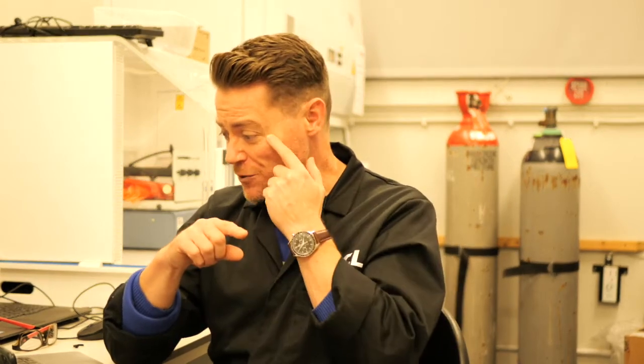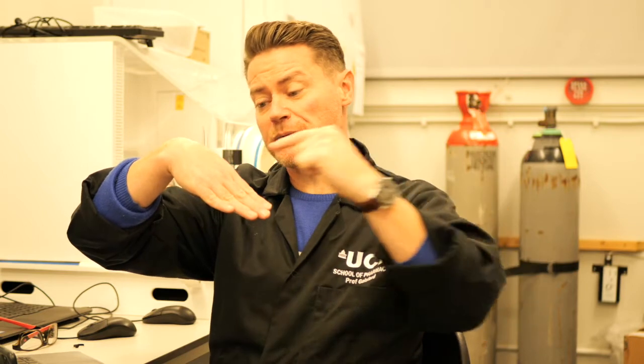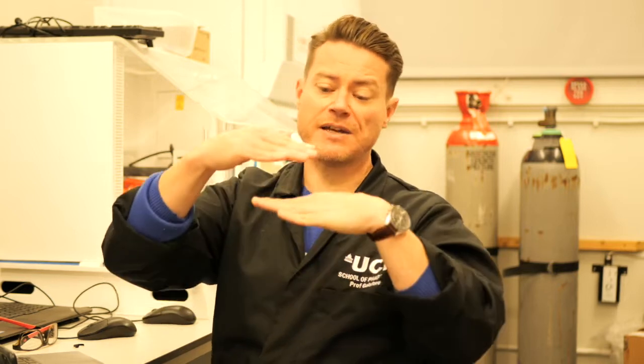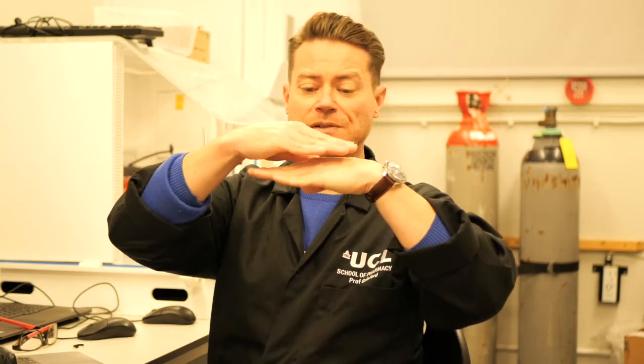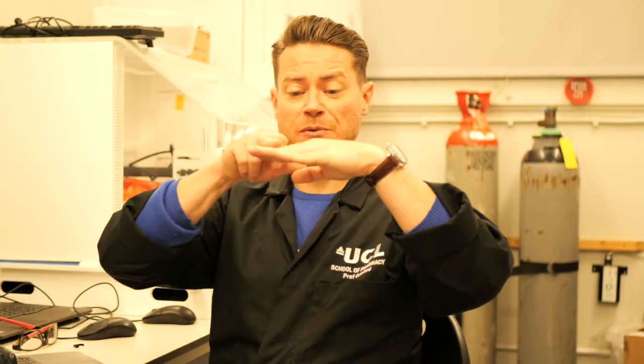It's mounted onto a thing called a cantilever, so a cantilever can move up and down, and on the back of the cantilever there is a mirror at an angle. So the way the atomic force microscope works is it takes a laser and shines that laser at the cantilever tip. It's focused on the mirror, and so the mirror will then reflect the laser beam back to a detector. The reason it does that is because as you put the tip in close contact with your sample and you move it, if your sample is rough, the tip will go up and down over the contours of the surface of your material, but that movement is really small.